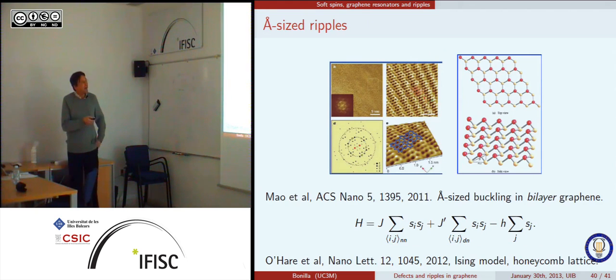More about ripples: this is another experiment, this time at Harvard, with a graphene bilayer. So instead of a monolayer, there were two layers. And they observe ripples which are the size of angstroms. So here you have a side view. One of the sublattices of atoms is up and the other down. There are some explanations about how you could use the Ising model on a honeycomb lattice to do that. For instance, these people just use an Ising model with an antiferromagnetic nearest neighbor interaction. Since it is antiferromagnetic, it would try to do this. The nearest neighbors always belong to the different sublattice, so you put one of them up, the other down, and that minimizes the energy.